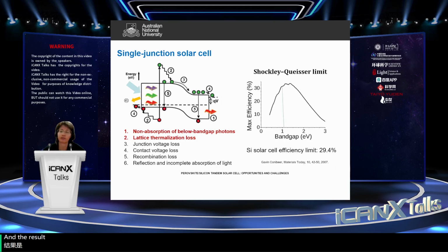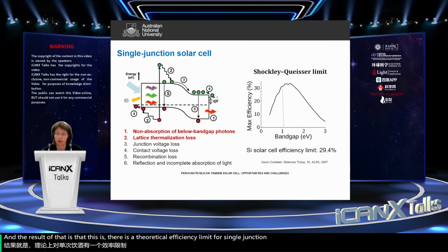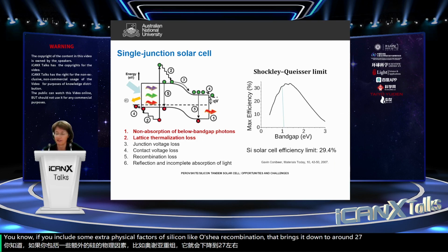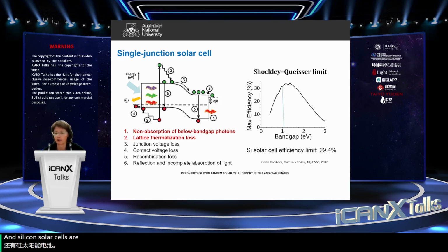And the result of that is that there is a theoretical efficiency limit for single junction solar cells. This is called the Shockley-Queisser limit, and for a silicon solar cell, because of its band gap of about 1.1 electron volts, the theoretical efficiency limit is around 29%. Now, if you include some extra physical factors of silicon, like Auger recombination, that brings it down to around 27%, and silicon solar cells are already 26% efficient. So there's really nowhere to go with the efficiency of silicon solar cells.